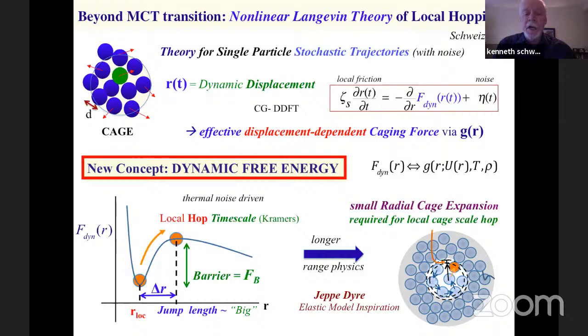So this was a nonlinear Langevin equation until maybe 5 or 6 years ago, in which we took seriously an idea of Jeppe Dyre that it's probably unlikely that this activated hop can happen without active participation of particles much farther away. In fact, if we take the theory seriously, the numbers that are predicted here, it's consistent with, in an average sense, not being able to realize this hop unless you have a small expansion of the cage. But you're in a dense system, so the only way to have a dynamic fluctuation that expands the cage a little bit is for the particles outside to move. And so the theory predicts that this radial cage expansion exists, and it's small, and we adopt the idea that it's required to allow a local hop.